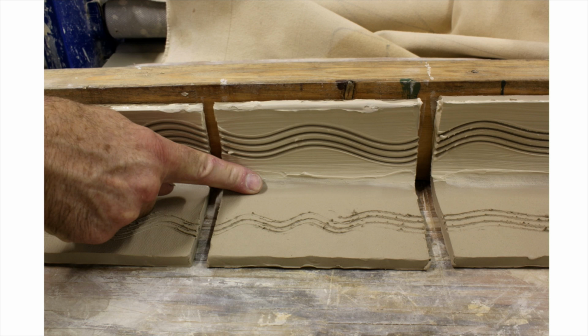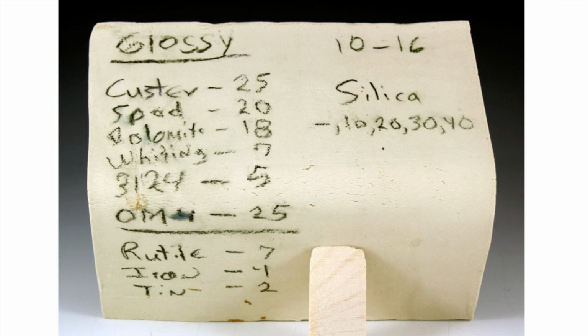So this is how the testing method works to adjust a glaze. First, you make a 6-inch tile with slip on the top half if you want to see how the glaze will respond over a slip, with textured lines on the top and the bottom made by dragging a fork through the clay, and then bend the tile into an L shape. After it is bisque fired, label the back of the tile with an underglaze pencil.